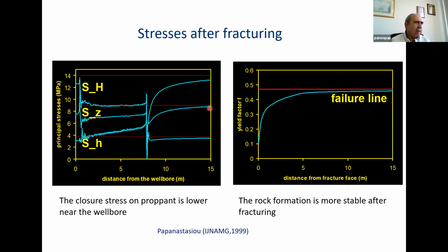These are the stresses before fracturing, far away ahead of the tip. And then after we fracture, the stresses are here, and you see they became closer. This can be seen clearly in this diagram, which shows how close we are to failure. Let's say that the failure line, which is defined by the rock strength, is the red line, and the blue line is the stress concentration, according to the Mohr-Coulomb criterion.